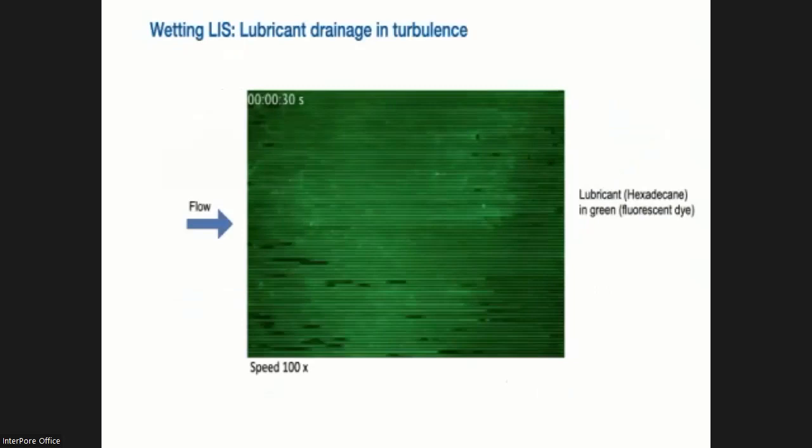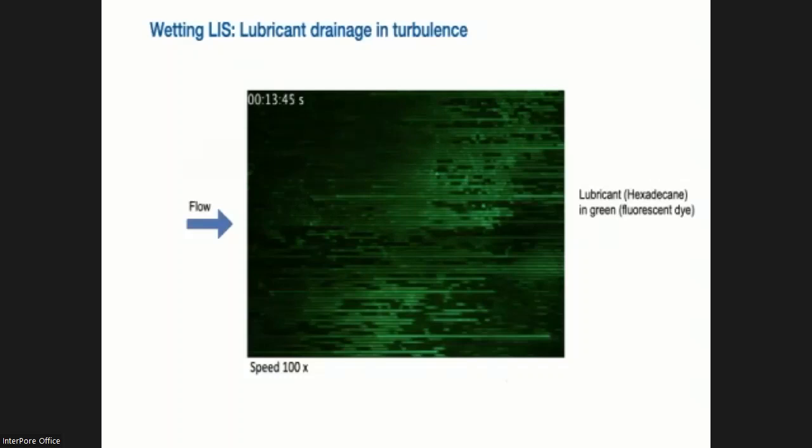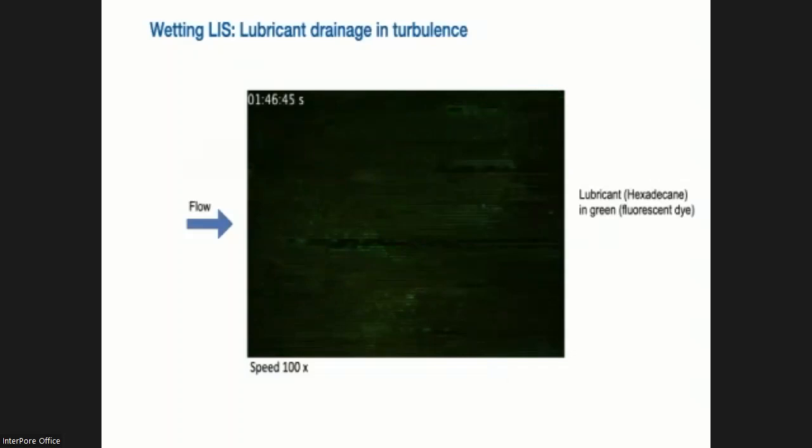So if we have this kind of chemistry, and then we look at how the interface behaves under turbulent flow, we see that there's an initial de-wetting. And these streaks are going to move slowly, but gradually there will be a complete drainage. So if we fast forward this one hour and look how it looks like after one and a half hour, we can see that most of the oil, essentially all of the oil is actually drained. There's only a very, very thin film at the bottom of the grooves.